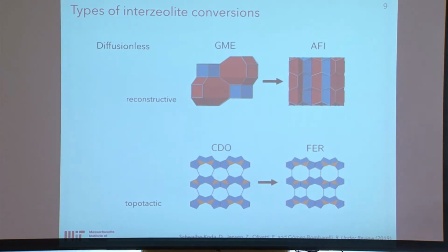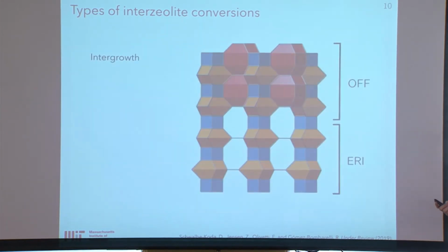We call them diffusionless because of their similarity with martensitic transformations in material science. They involve, for example, bonds being broken and reformed with low diffusion of atoms inside these crystals and unit cells. And also topotactic condensation of, for example, lamellar precursors to form 3D structures of zeolites. Finally, one last interzeolite relationship we found is the zeolite intergrowth, which relates 2 different frameworks through a stacking fault in the same crystalline material.